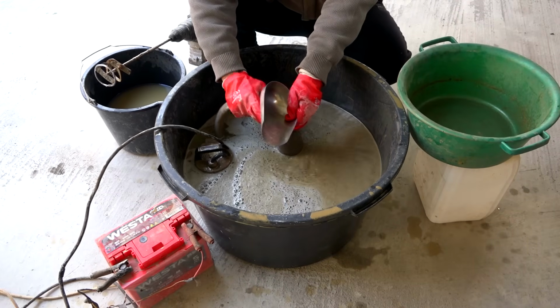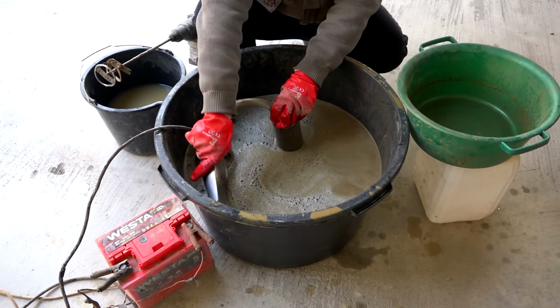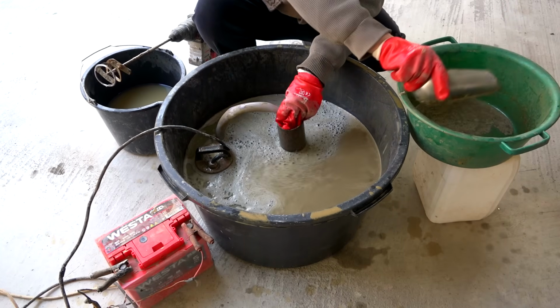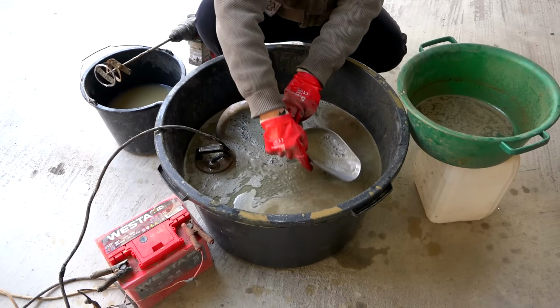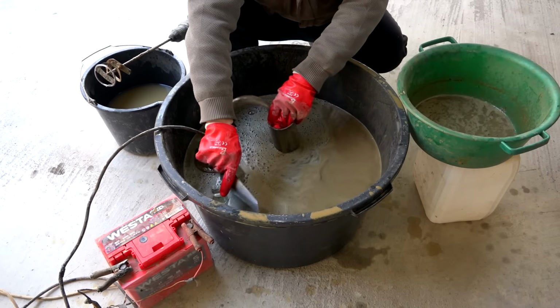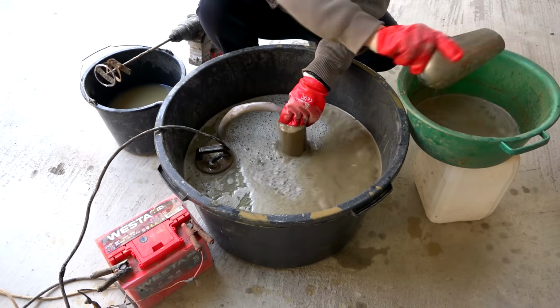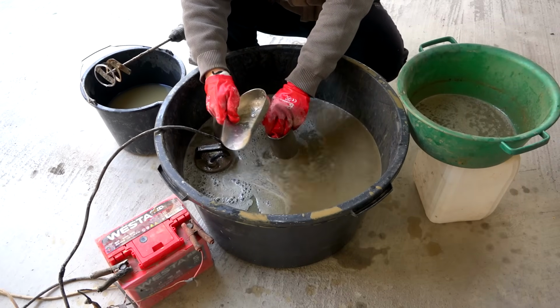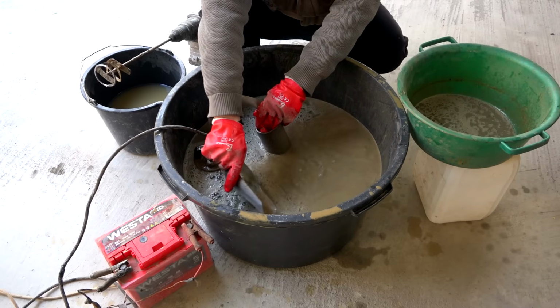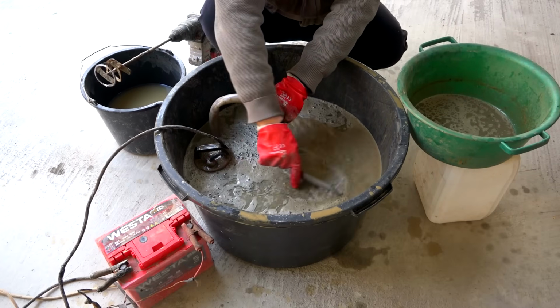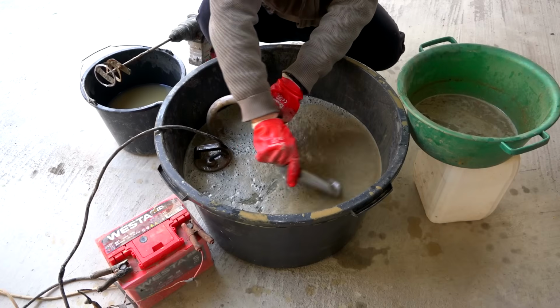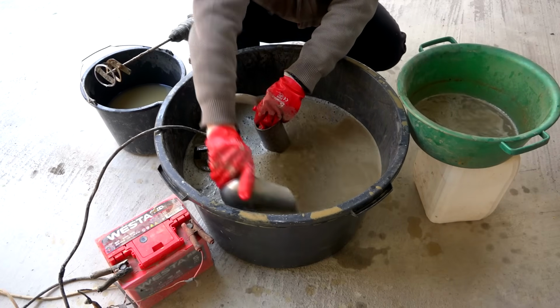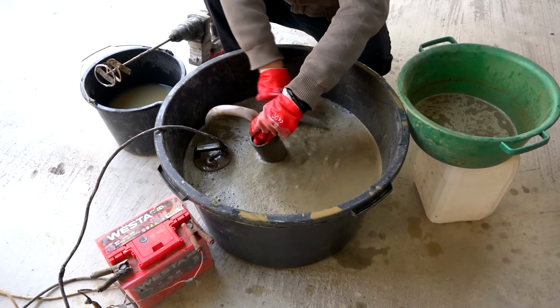Then I realized that simple mixing wasn't enough in this case, and I came up with a simple solution. Take a regular pipe and insert the pump hose into it, but not all the way, about 10 to 15 centimeters. Don't hold the pipe at a right angle or lower it all the way to the bottom. You need to control this process, creating intense circulation and a boiling effect on the pulp. Do you understand how it works?